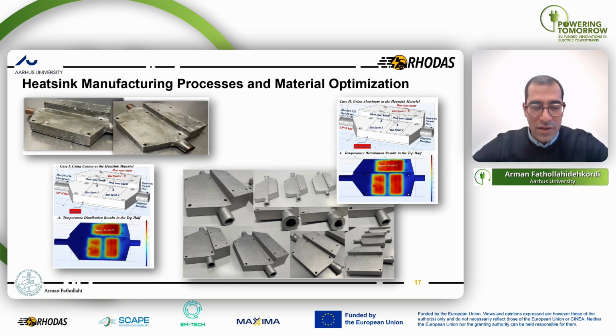So in this case, we changed it to aluminum, but this change we simulated, and you can see here the T maximum for the aluminum is something like 29, but for the copper is 26. Yes, definitely copper is better. But based on this restriction, we changed it to aluminum, and on the other side, we had a weight reduction of more than 60%. That could be an advantage for the whole system.